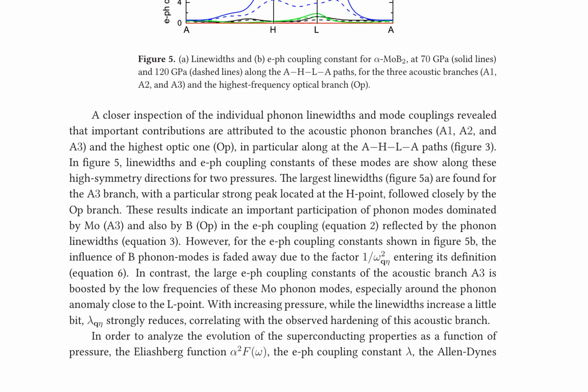In contrast, the large EPH coupling constants of the acoustic branch A3 are boosted by the low frequencies of these Mo phonon modes, especially around the phonon anomaly close to the L point. With increasing pressure, while the linewidths increase slightly, lambda q eta strongly reduces, correlating with the observed hardening of this acoustic branch. The analysis of the evolution of superconducting properties as a function of pressure is facilitated by the calculation of the Eliashberg function alpha squared F of omega, the EPH coupling constant lambda, and the Allen-Dynes formula for the critical temperature Tc.